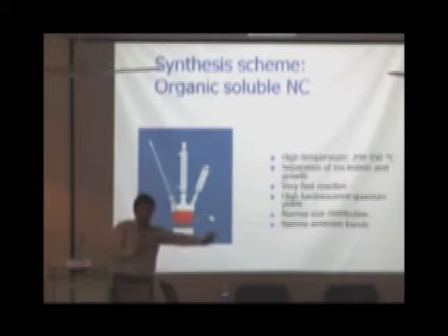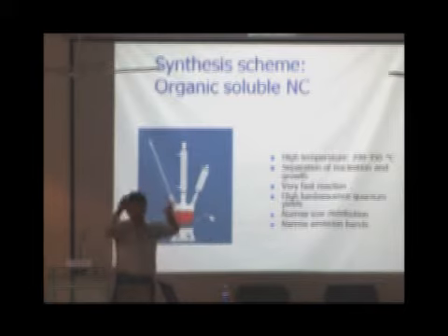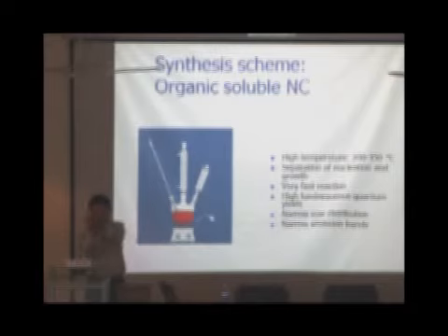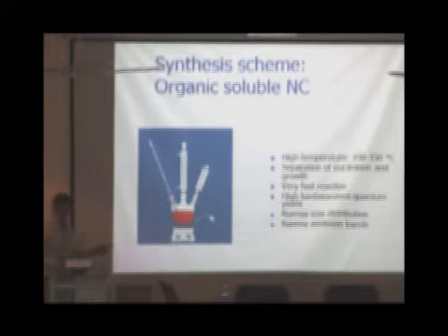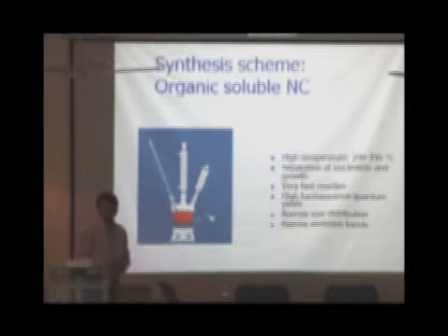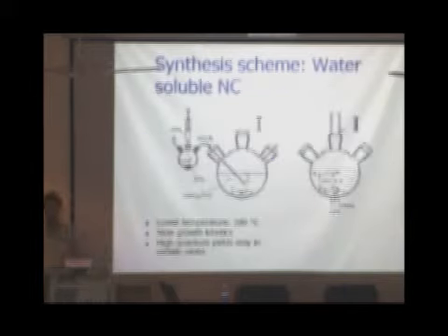So at one point you are making the nuclei and then just growing them over a certain period of time. If you were to make some nuclei at a later time as well, then you would get a size distribution. So these kinds of high temperature methods ensure that you separate the nucleation and the growth, and you can get more monodispersed particles. I'll show you some of the transmission electron micrographs, and you can see that these are actually less than 5% size monodispersed.